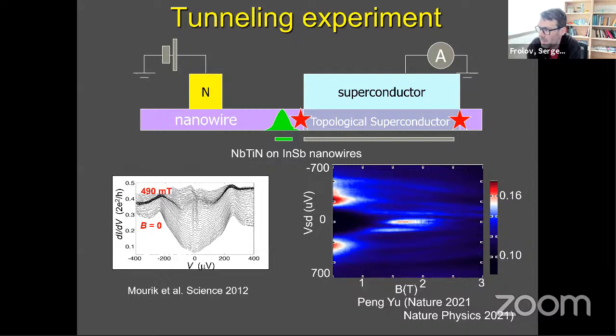But indium arsenide tends to have a lower mean free path, a lower g factor, a little bit lower spin orbit, a little bit higher effective electron mass. And those nanowires often have crystalline defects in them, where the crystal structure rotates along the wire, and that probably contributes to shorter mean free path as well. So indium arsenide and antimonide are pretty similar, but antimonide still wins.